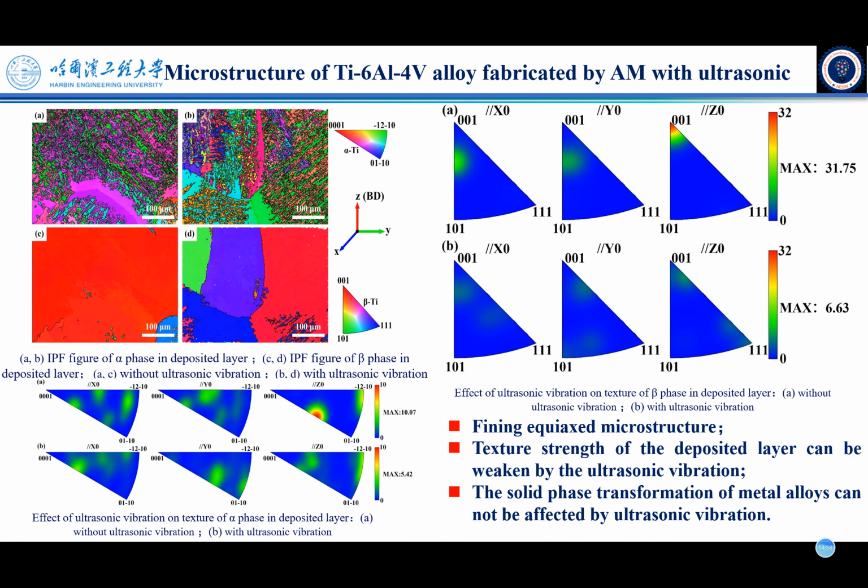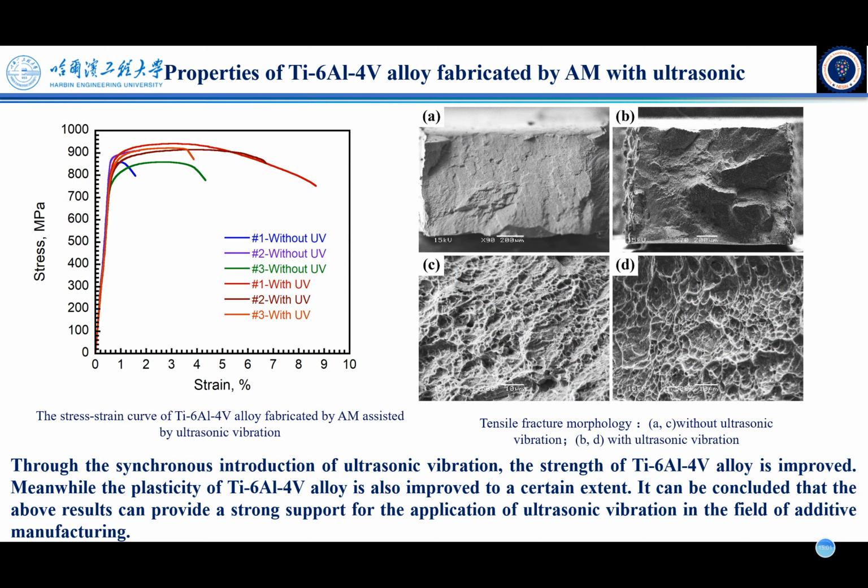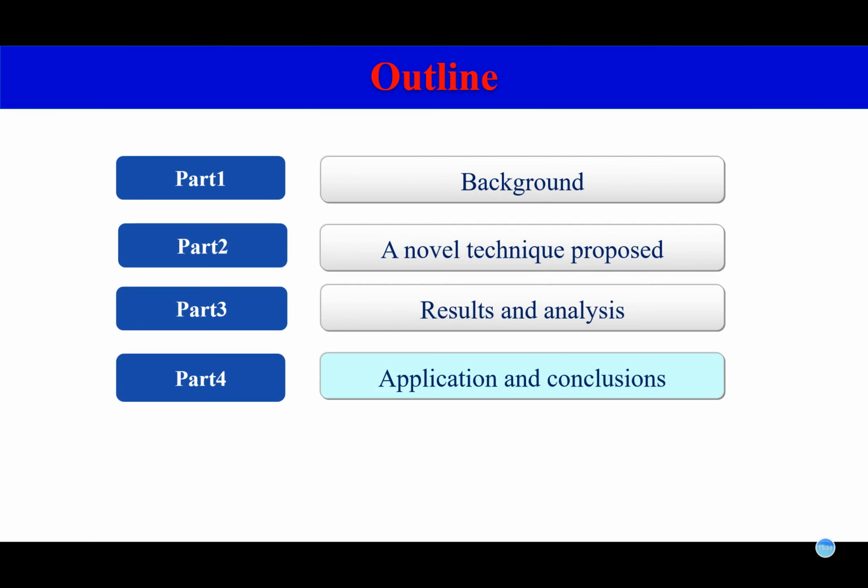ultrasonic vibration, though the solid phase transformation of metal alloys cannot be affected by ultrasonic vibration. Through the introduction of ultrasonic vibration, the strength of the titanium alloy is improved. Meanwhile, the plasticity of the titanium alloy is also improved to a certain extent. It can be concluded that the above results can provide strong support for the application of ultrasonic vibration in the field of additive